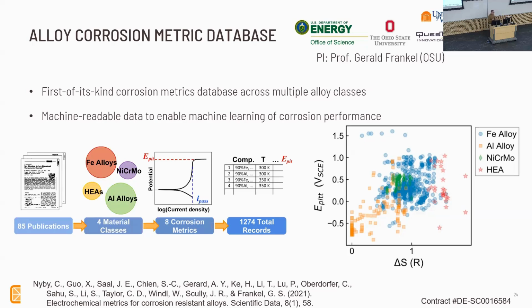So when you do measurements of corrosion, there's also a lot of environmental considerations in terms of what temperature you're going to measure at, how much salt, what's your pH of the solution. So it becomes a very complex and messy set of parameters that feed into coming up with one measurement of a corrosion metric, of which there are actually at least 8 of them.